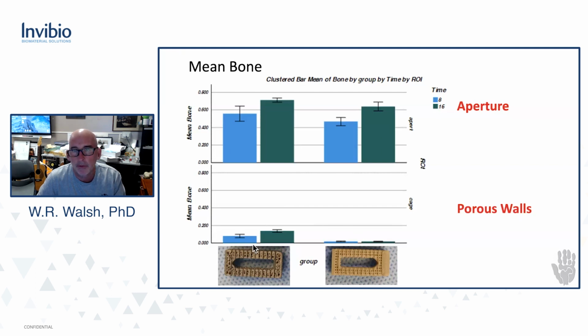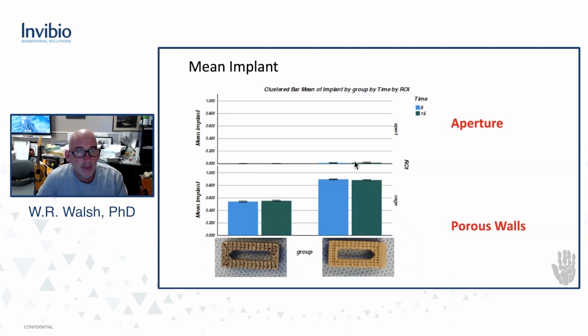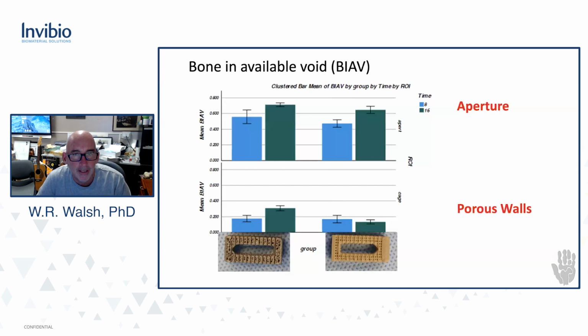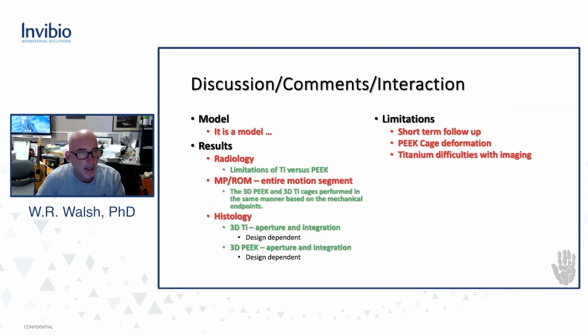Just like the cancellous bone from all my studies from the year 2000, the bone to go into cancellous is quite difficult. This is how much implant there is. In the aperture, obviously there's no implant, but in the titanium, it was about 50% implant and 50% porous, where the PEEK was about 90% implant and 10% porous. So when we normalize bone in the available void, the aperture data does not change, but the bone in the available void demonstrates that both materials supported osseointegration into the macro topography that was presented.